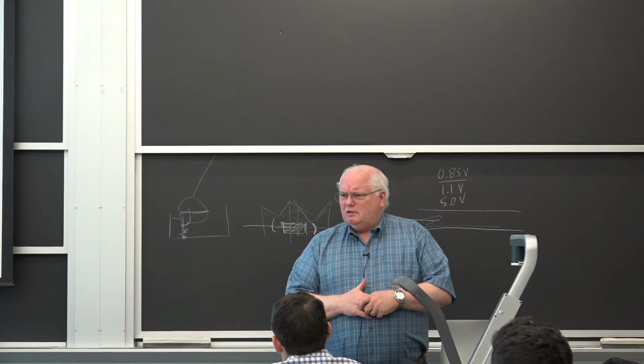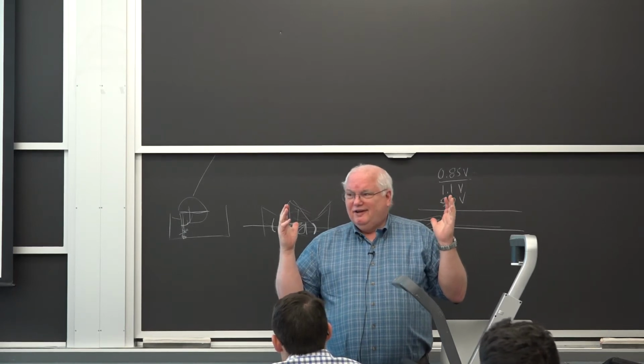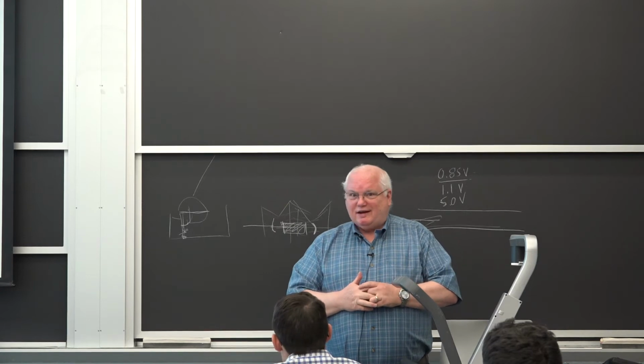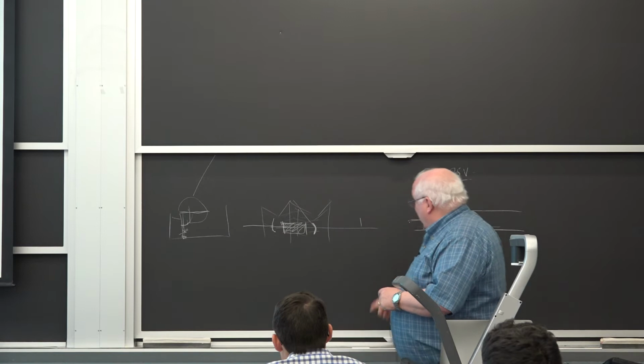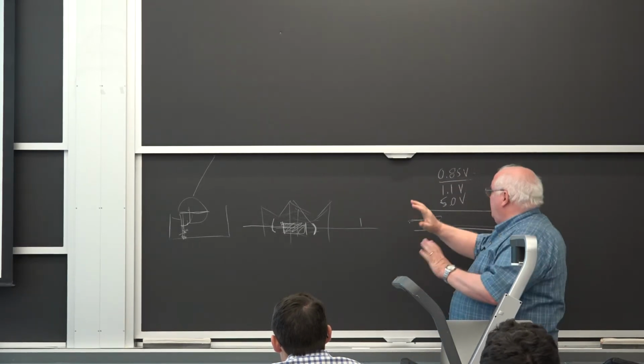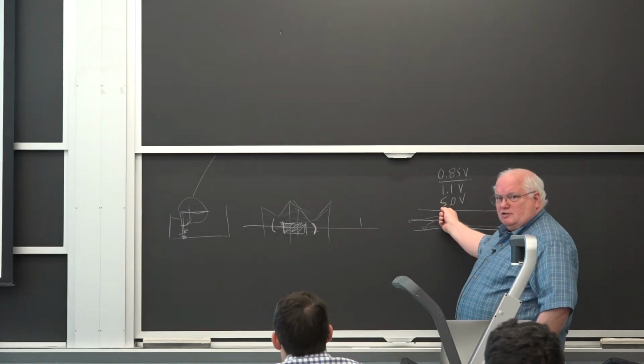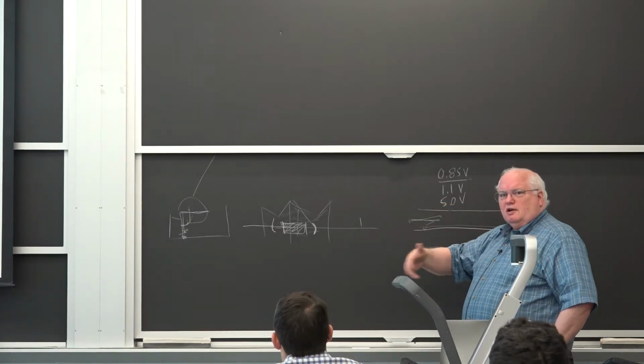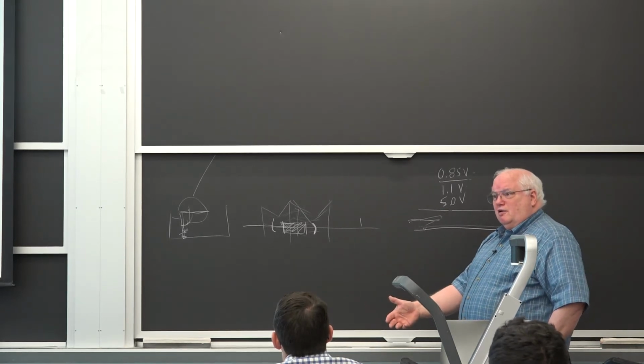But they were finding pitting on the positive electrode of the DC circuit. And I said, well, what do you expect? And they said, well, we need a material that won't do this. I said, at 100 volts, okay, there is no way, there's no material in the world. I mean, the most stable oxides are only 5 or 6 volts on an electrochemical equivalent, okay? And they were using 100 volts.